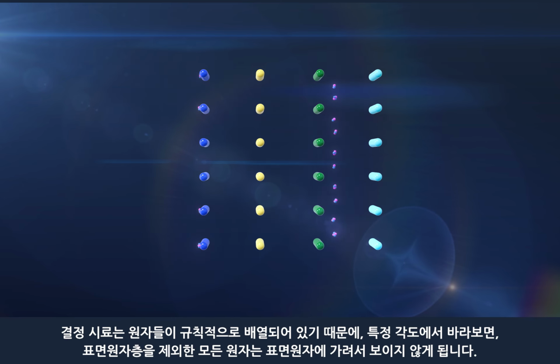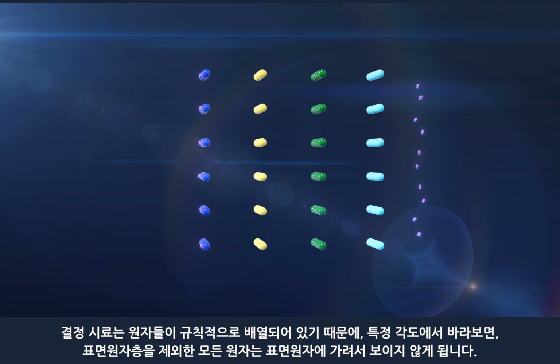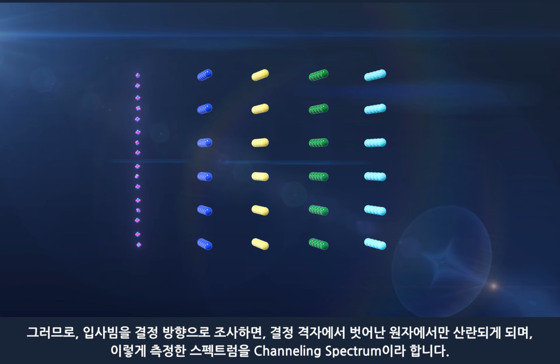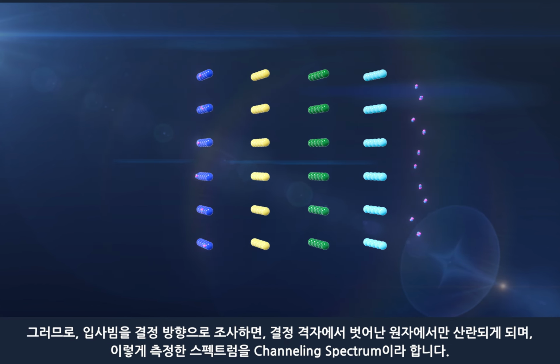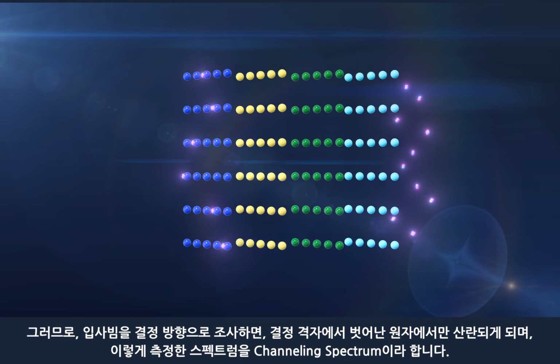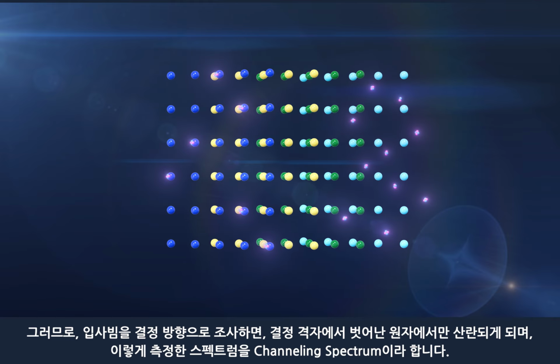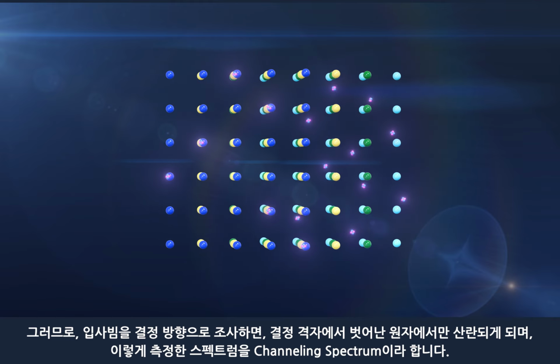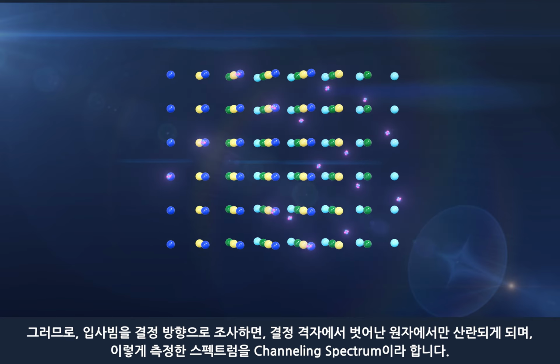Because the atoms of the crystal samples are lined up side by side, when viewed from a certain angle, all atoms except those in the surface atomic layer are hidden by the surface atoms. Therefore, when the incident beam is irradiated in the lattice direction of the crystal, it is scattered only from the surface atoms and atoms that are displaced from the crystal lattice, and the spectrum measured in this manner is called a channeling spectrum.